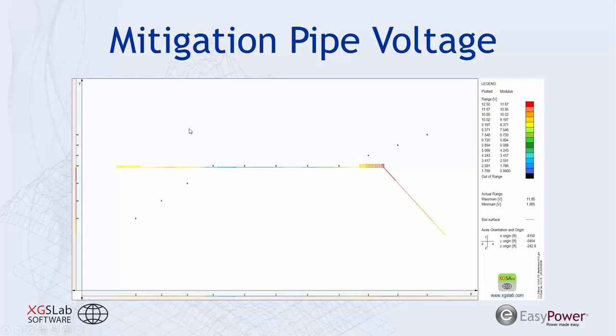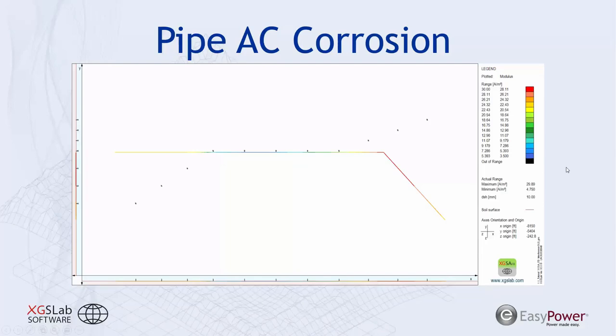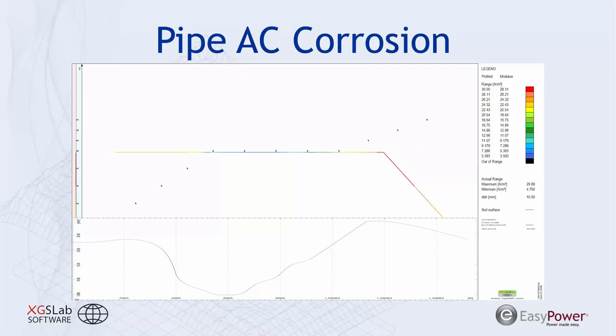And one thing to note too, when you're making these sorts of connections, you may not be able to directly connect any sort of grounding to the pipeline. You may need to consider existing cathodic protection, or that whatever you're introducing can cause new corrosion issues for the pipeline. So maybe you need to use steel rods instead of using a copper plated rod for your grounding. So let's see what this does for the AC corrosion. Here we can see that on the pipeline we are just barely below that 30 amps per meter squared value. Here's another view of the pipeline's amps per meter squared value. And by incorporating those ground rods throughout the pipeline, we're able to keep it just below the level where we'd expect to see corrosion occurring on that pipeline.